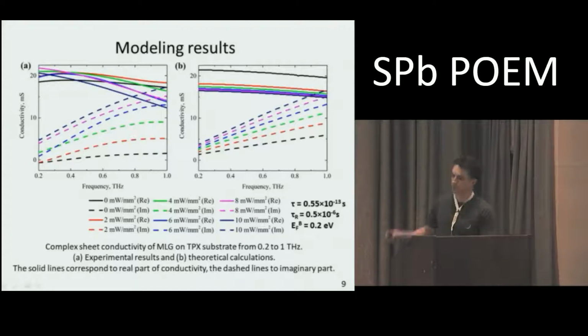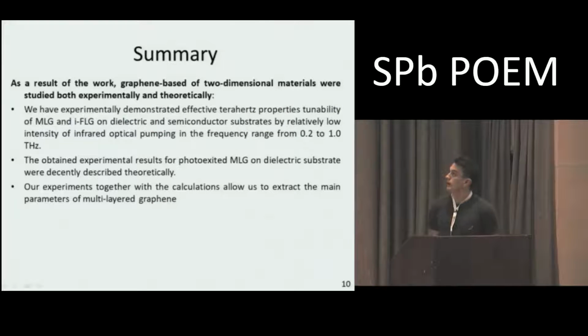So, in summary, we investigated the graphene-based two-dimensional materials theoretically and experimentally. We demonstrated effective tunability of terahertz properties by using external optical pumping of modest intensity. Obtained results were decently approximated theoretically, and we extracted some main parameters of the investigated material.